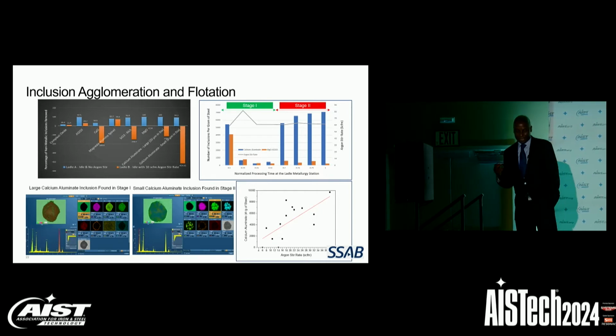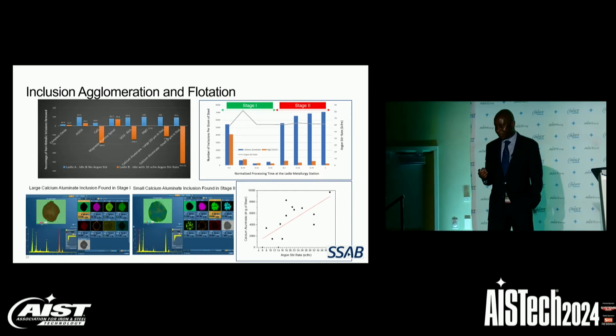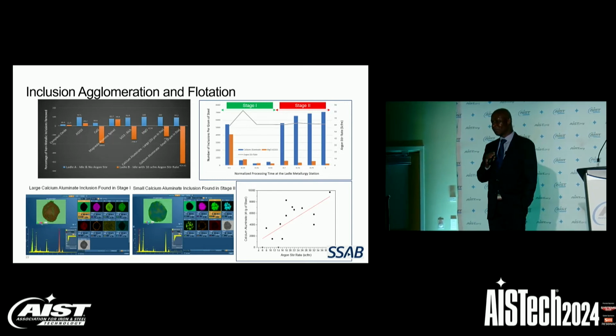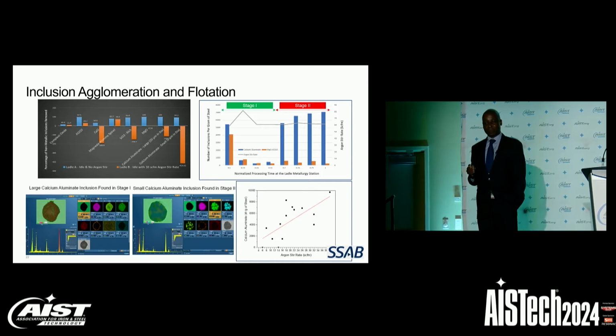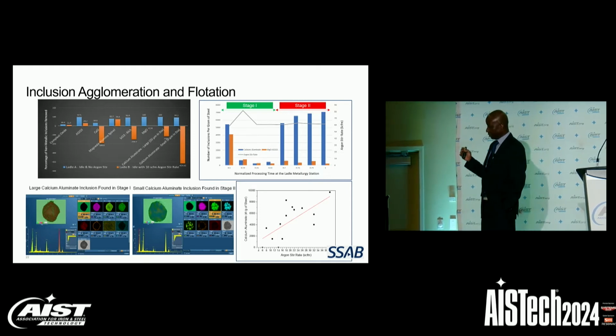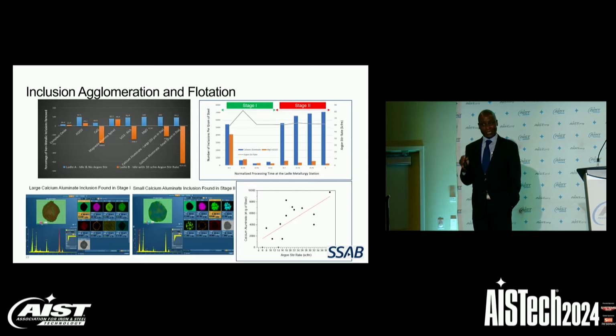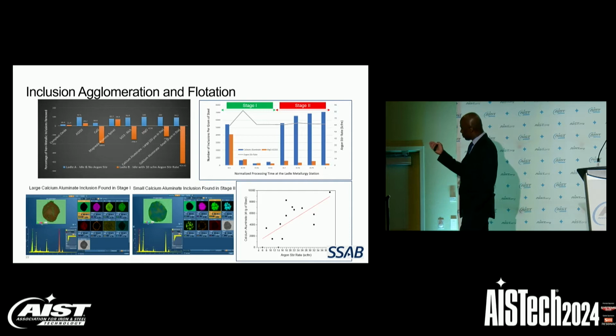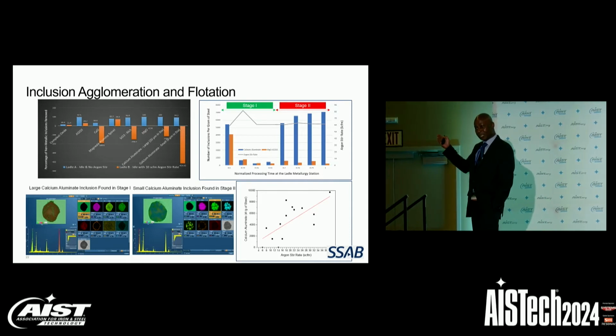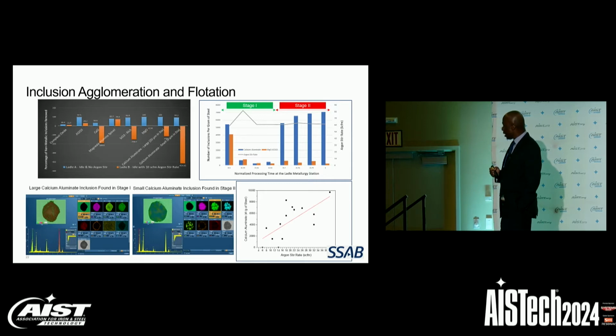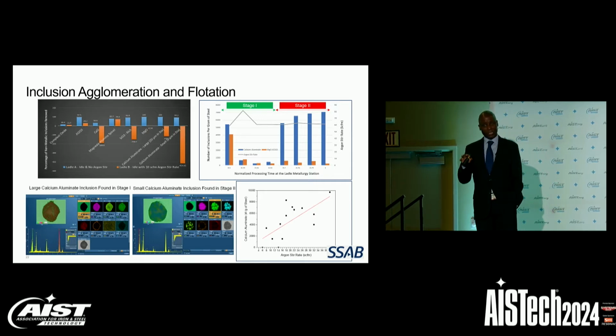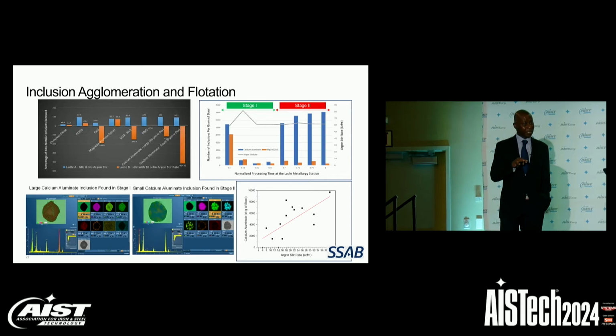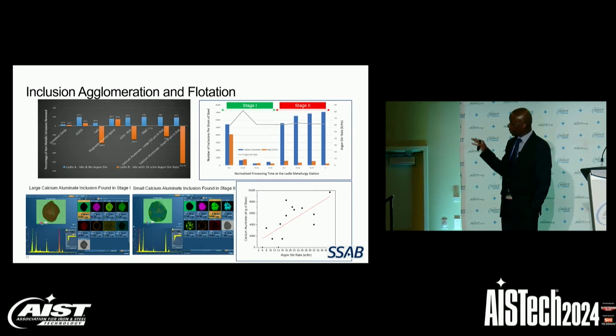And then in our second experiment, we had a ladle of steel, and we sampled the steel from the beginning of refining to the end of refining. And we found out that the refining process can be divided into two regions, or two stages. Stage one is where we had very rapid decline in the population densities of non-metallic inclusions. And stage two, where we have significant, gradual increases in non-metallic inclusions. We also found that the inclusions in stage one were significantly larger in size compared to the inclusions in stage two.